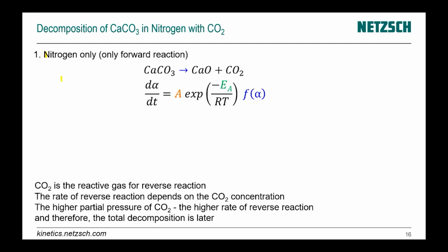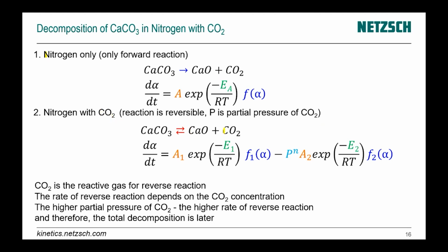Here, that was nitrogen. The second part is nitrogen with CO2. If we have a partial pressure of carbon dioxide, then in the presence of carbon dioxide we have a reverse reaction, and the total reaction will be slow. And if the concentration, or just the partial pressure, of carbon dioxide is higher, then the rate of the reverse reaction will be higher, and then the total reaction rate will be slow. In order to see how this influences the backward reaction, we have here the term: the partial pressure of carbon dioxide to the power n, where n is a fit parameter.